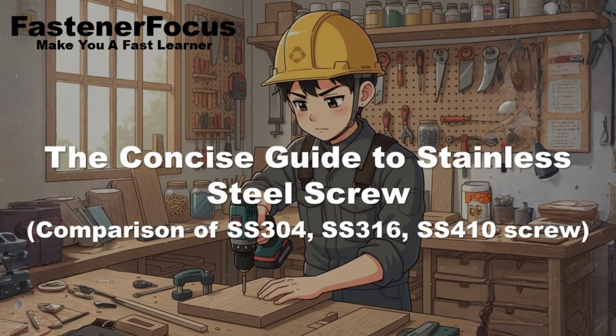So what are the necessary mitigation methods for galvanic corrosion? How do you stop this from happening? Well, the standard practice is isolation. This means using non-conductive washers, such as thick EPDM rubber or plastic, and bushings to physically separate the stainless steel fastener from the less noble metal.